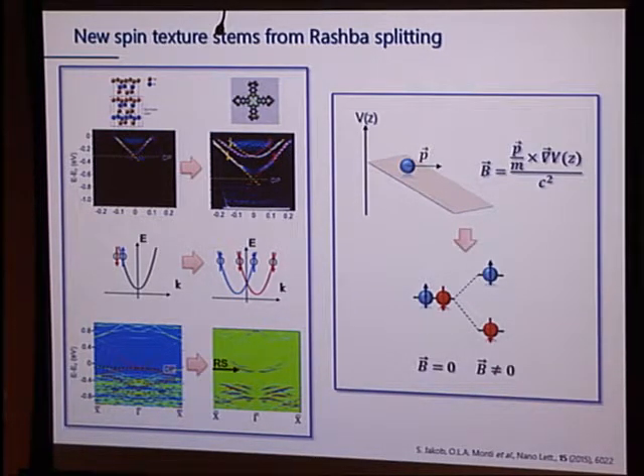And that must then also depend on where you do this in the band structure, because you get different momentum, different velocity, depending on where you are in the band structure. So, for example, at gamma, where p is 0, you would not expect any spin splitting, and lo and behold, you don't. Your substrate is not magnetic anymore. Not at all. This is a non-magnetic bismuth selenide. So what defines the direction of that electron motion that creates the magnetic field? The direction is the in-plane direction. Because it's a layered material, you're purely in that first layer. That's the momentum direction that we measure in the band structure, right?